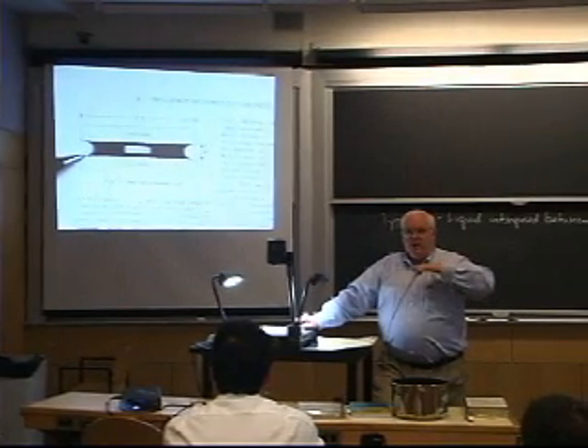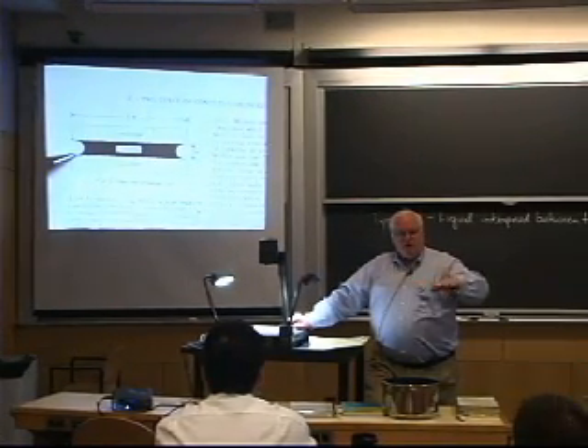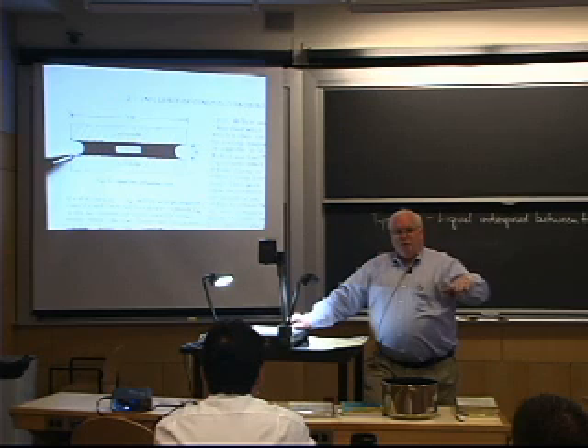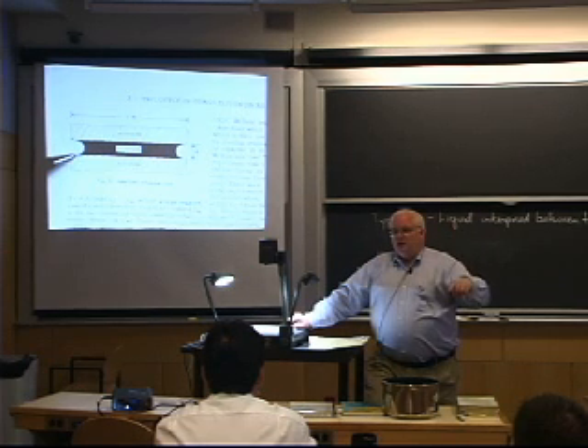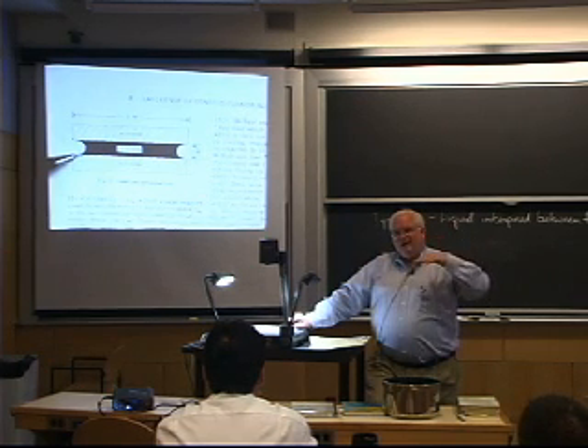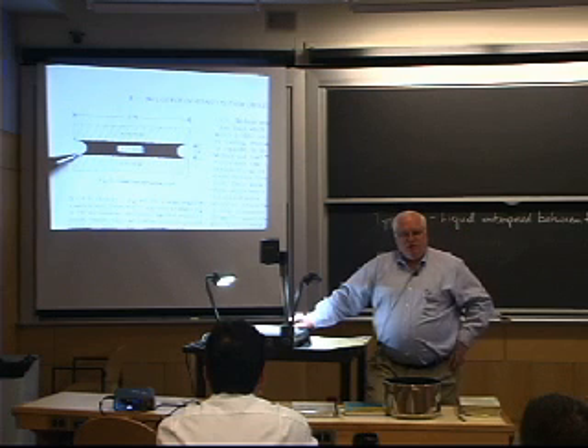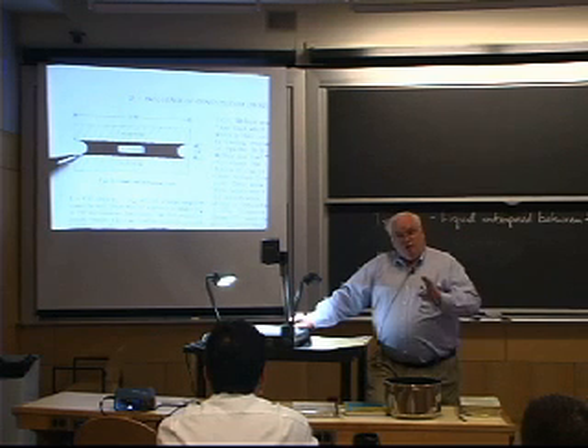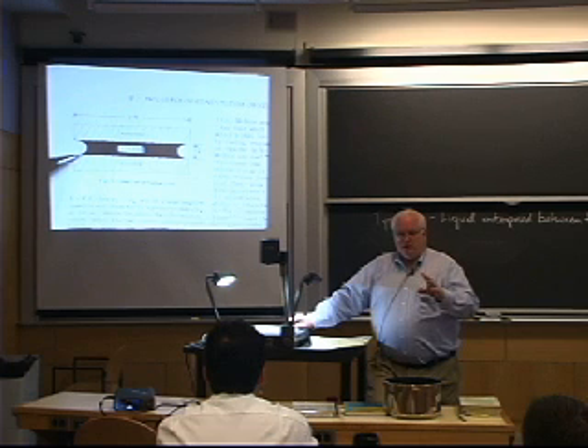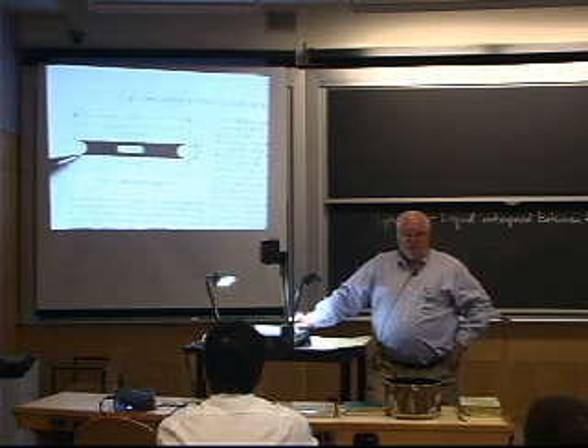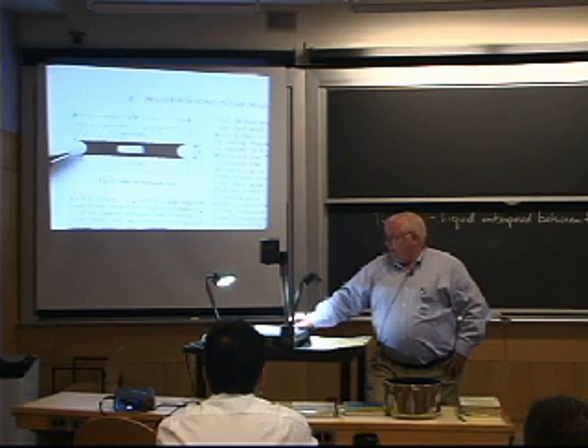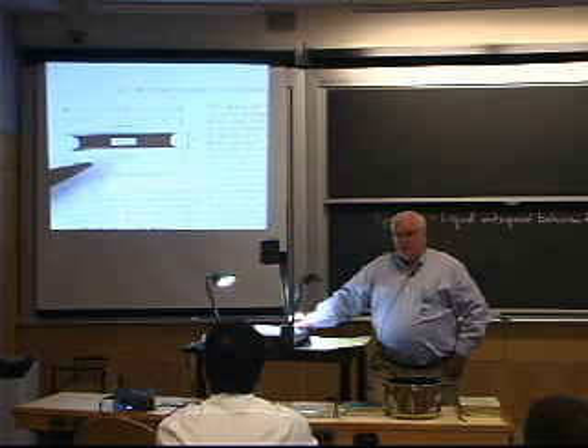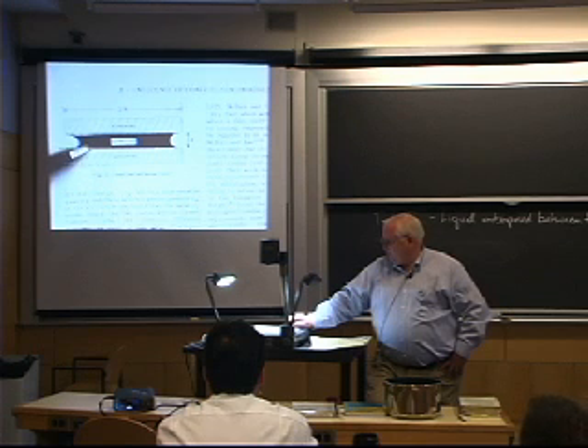If I was talking about an ultra clean metal surface with no oxygen on it, you might be talking about a primary bond between oxygen and the metal. But we're talking about an oxide surface, and we're really going to be talking about van der Waals bonding. Now remember, van der Waals bonding with an energy of 1/10 to 2/10 of an electron volt per atom potentially has the strength capability of 100,000 pounds per square inch. We don't always get that with adhesive bonding. As we know, in most bonding, we only get about 1/10 of the potential chemical bond strength.